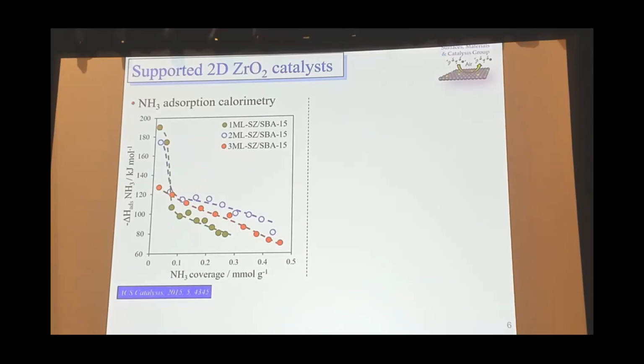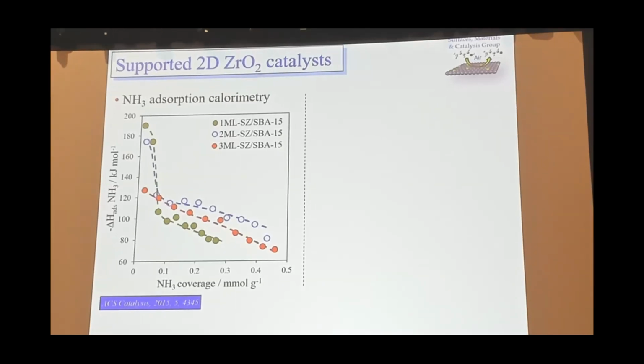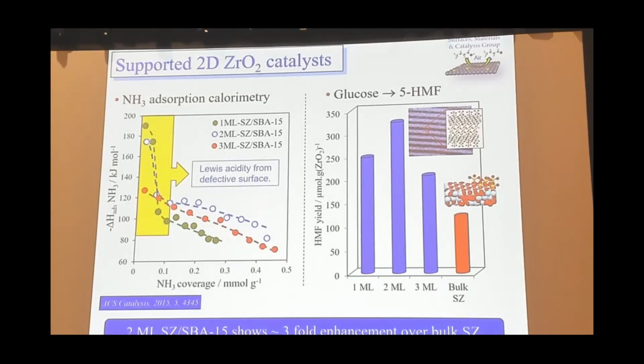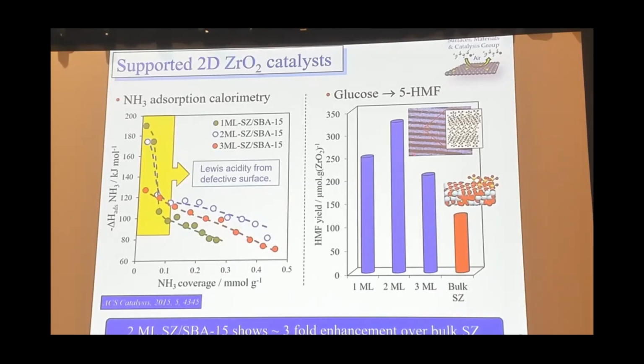What you can see is the 1, 2 layers is we have a small number of strong acid sites. So we believe this comes from the first couple of layers being completely fit. And then once you get 3 layers, it starts to then look like what a bulk zirconia material would appear. So by tuning the thickness of these films, you can tune the acidity of the material. And this also pans out in the catalysis.